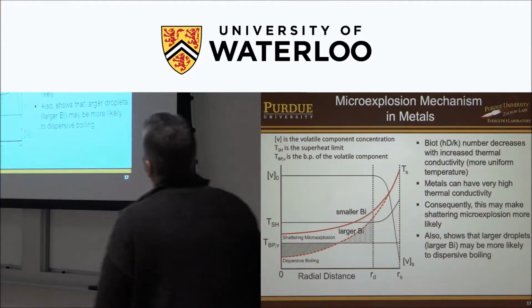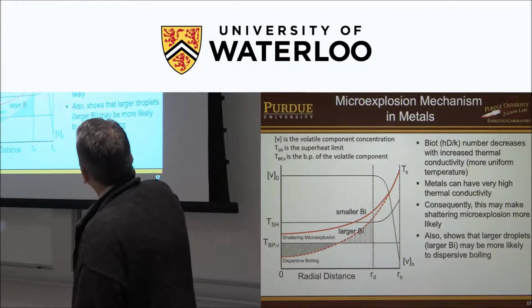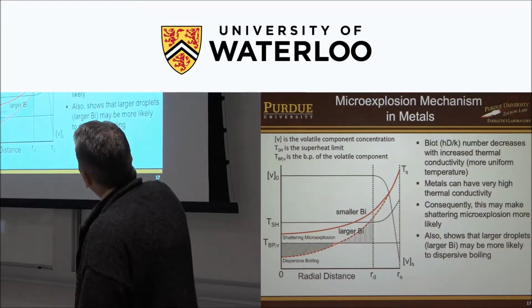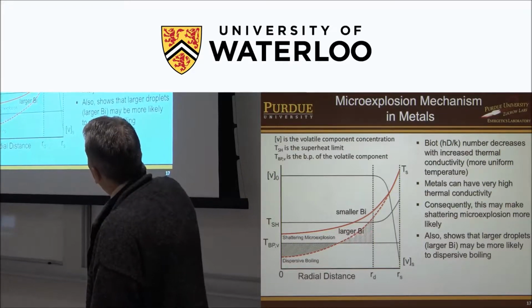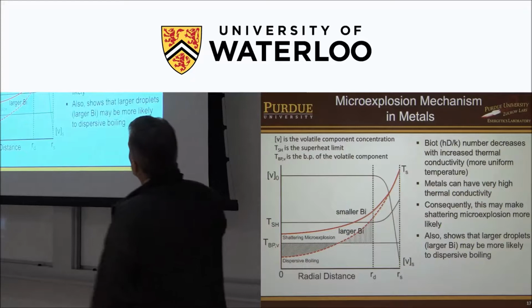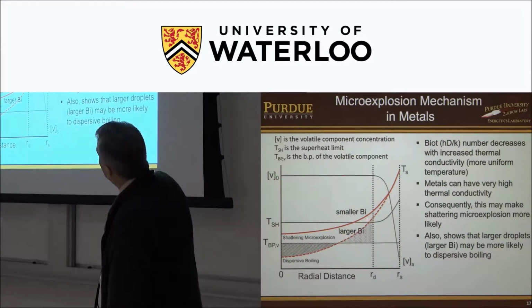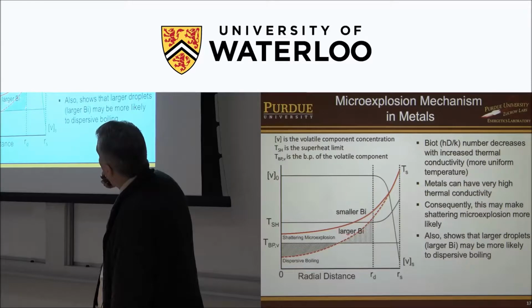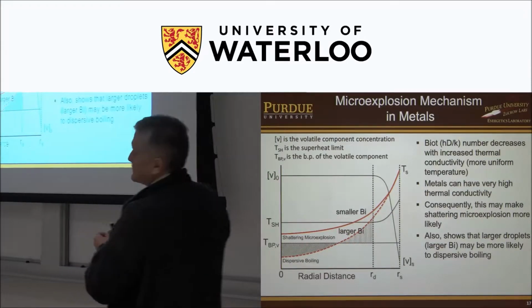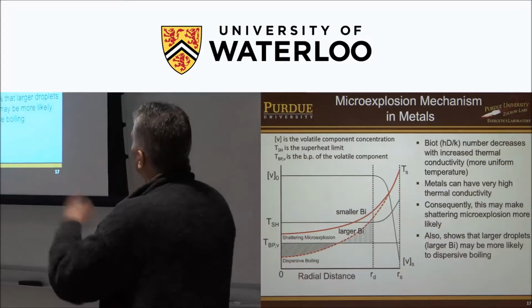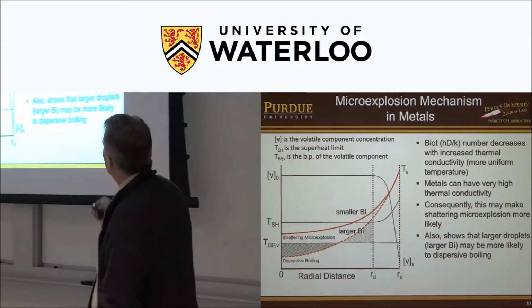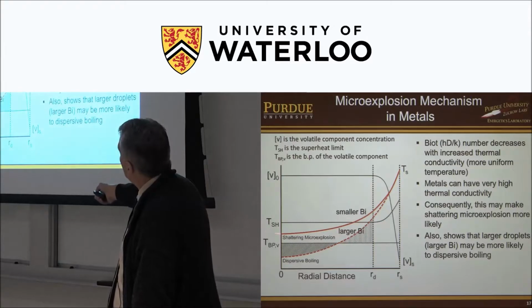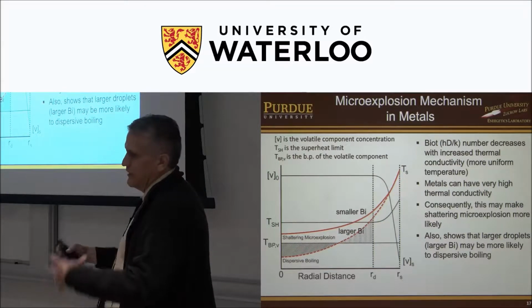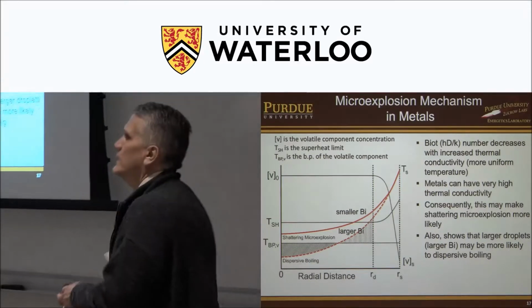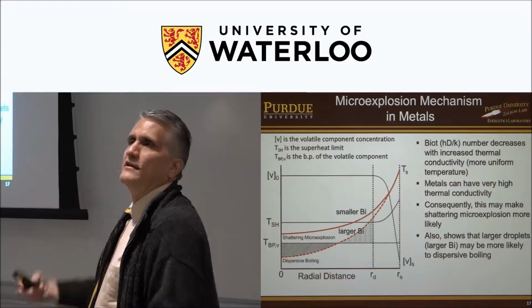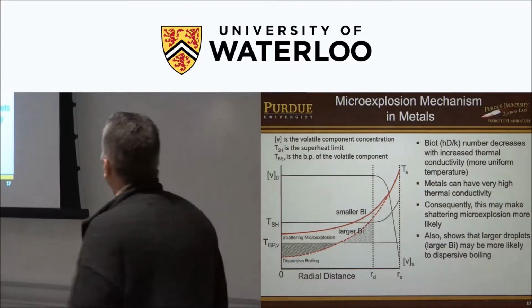That's this TSH. And so for dispersive boiling, you may have part of that droplet above the boiling point of the volatile component. That's what this line is. And so when that exceeds the superheat limit, this region will flash to gas, but not the whole droplet. And you'll have this dispersive boiling, kind of volcanic type of boiling. And in the other case, with the shattering microexplosion, you could have pretty much the entire core superheated. You exceed that superheat limit, and that whole core flashes to gas and shatters the droplet.